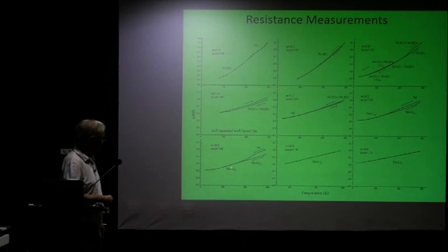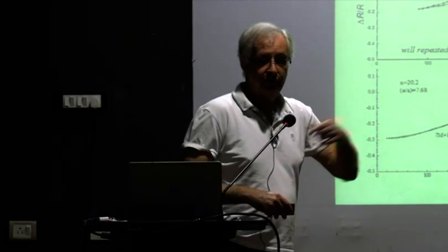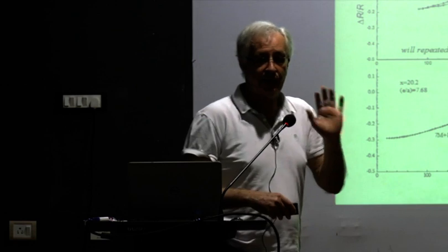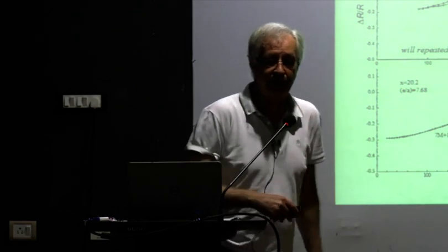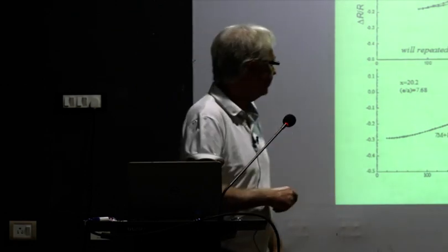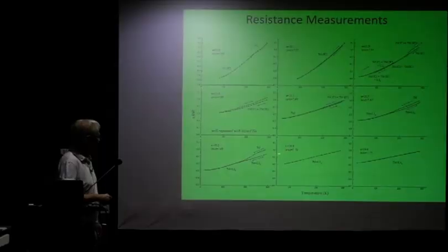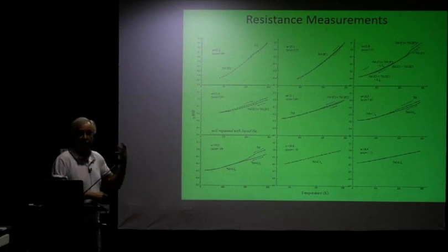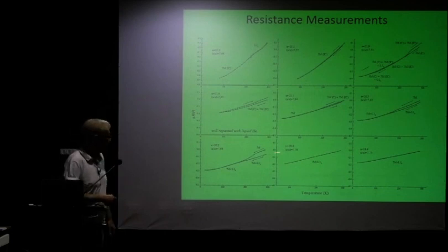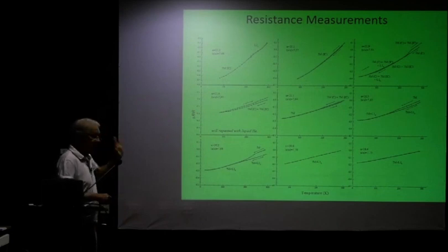And the resistance, the fact that it retraces, means that that structure remains stable. Goes back and forth. Nothing further changes. No, there's no new scattering mechanism. But then it will start changing up there somewhere. But what happens? This is the forward transformation of some intermartensitic transition going on, and the reverse transition is somewhere up further.